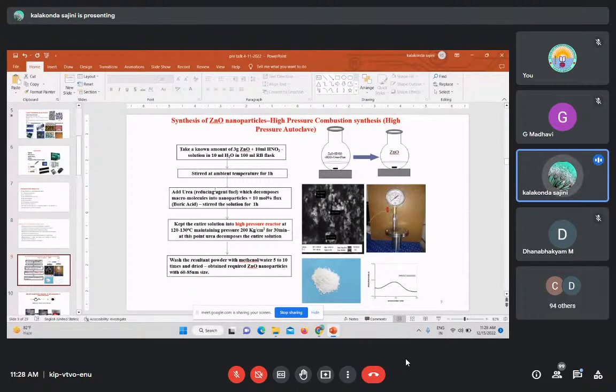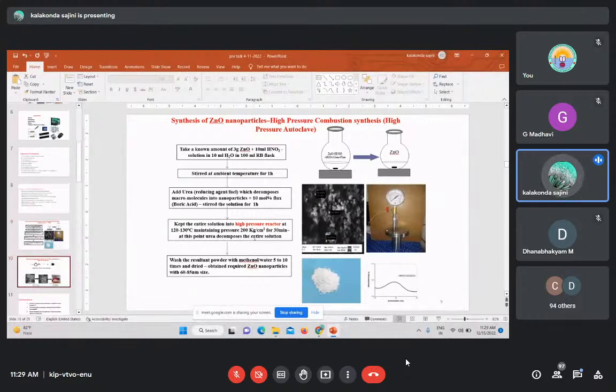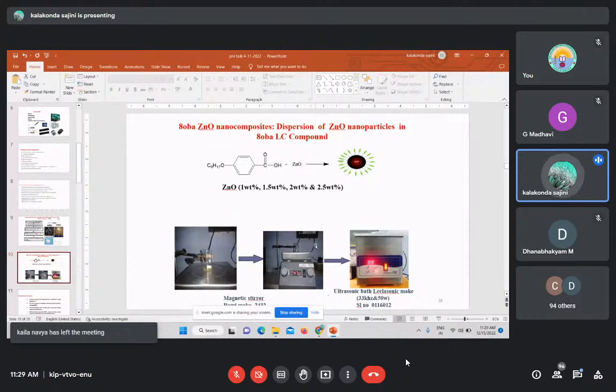In this method, first I have taken zinc nitrate in a round bottom flask, and I have added 10 ml of HNO3 and 10 ml of water, and stirred at a temperature of about 60 to 80 degrees for 1 hour. I have added urea, which acts as a reducing agent, so that the nanoparticles are reduced into small sizes by using the high pressure reactor at 120 to 130 degrees temperature and pressure. Also, by applying more pressure, we can synthesize the nanoparticles. And these are the various instruments I have used for synthesizing the nanoparticles.